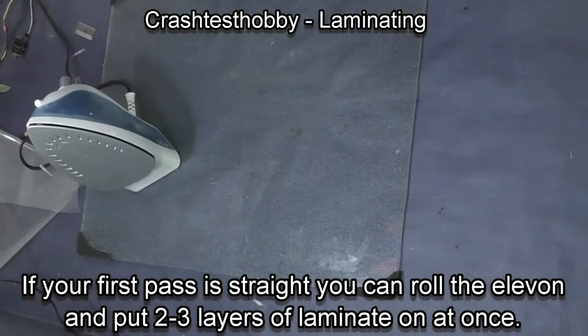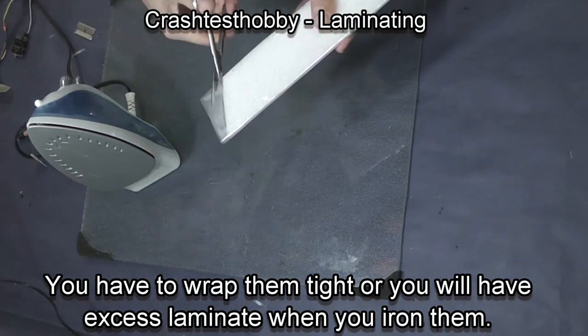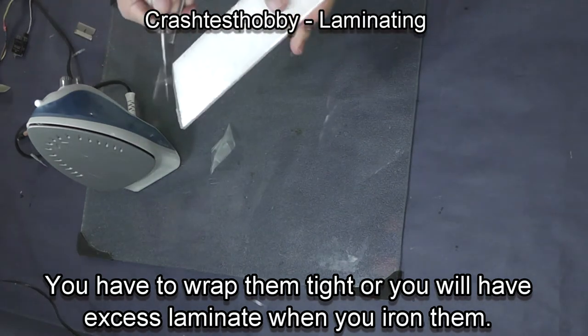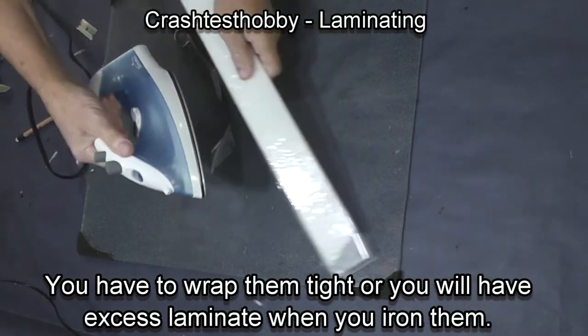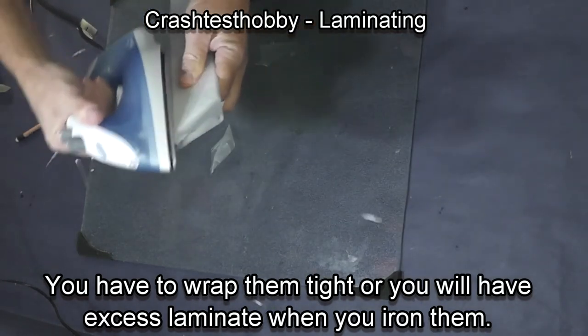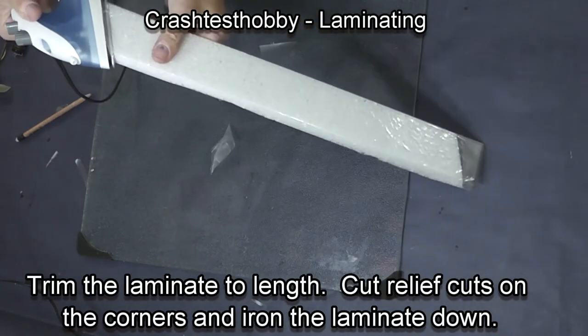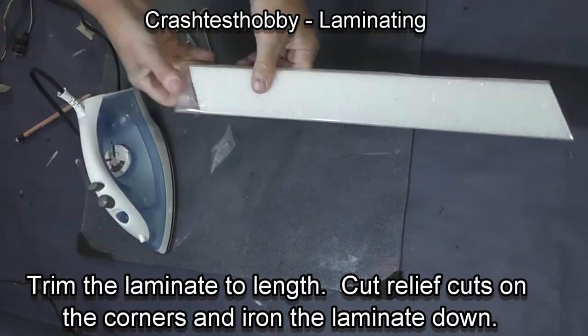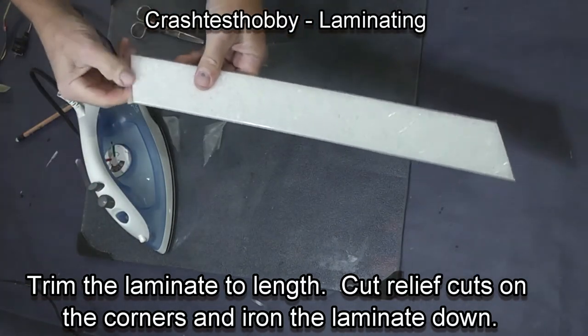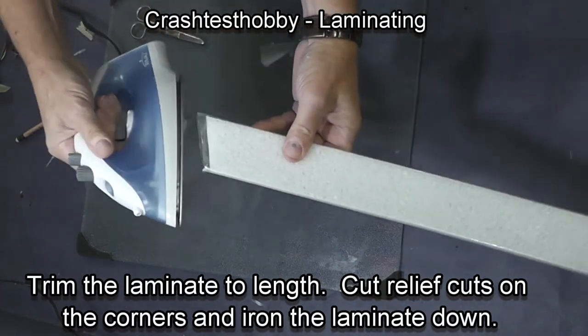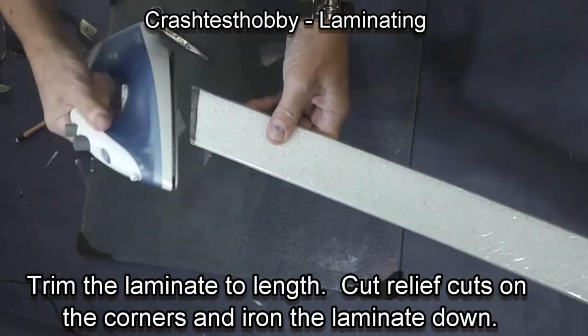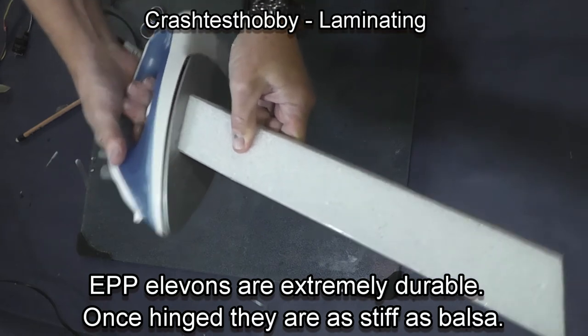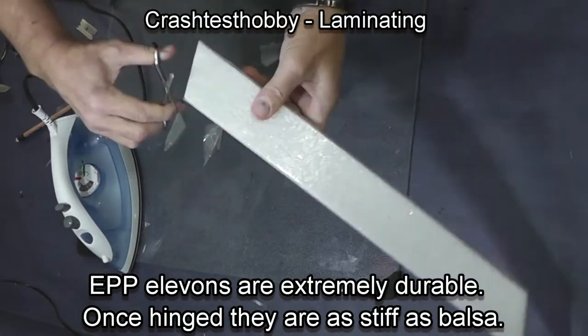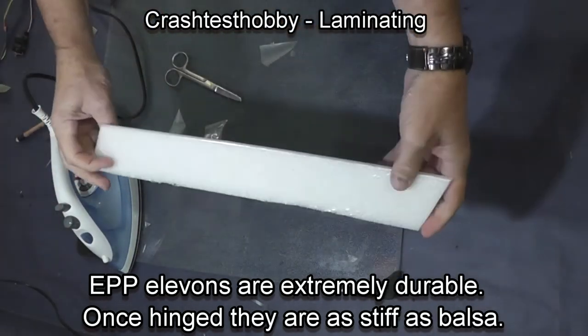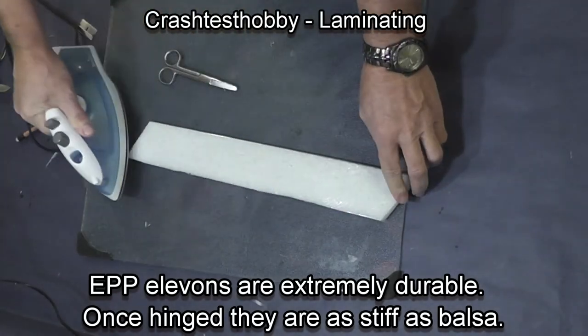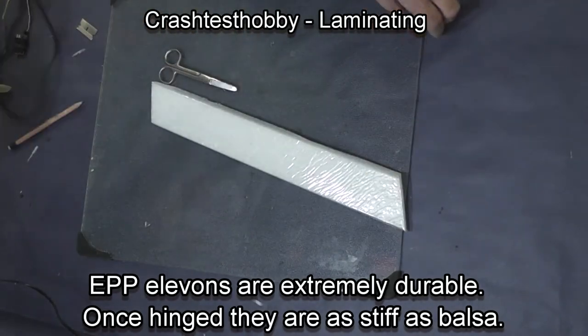But the big trick is keeping your iron cool. The elevon is so thin that extra heat tends to melt the elevon worse than it does when you're working on the wing. And it also makes it so that the elevon starts to have wrinkles and to bow. Once again, make your relief cuts on the corners and then iron around the edges. I was worried the larger iron would be hard to do, and I didn't have any more trouble with the bigger iron than I had with the small one.